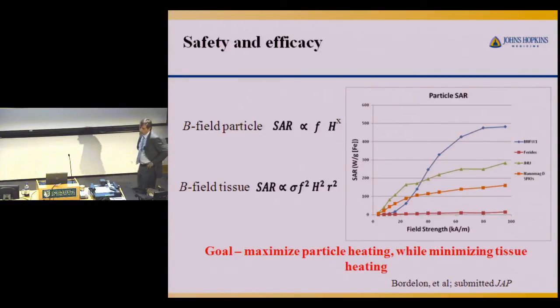When we put different particle formulations in an AC magnetic field, they're all iron oxides. They're all dextran or starch iron oxides. For some reason, we don't see the same result. That's because the magnetic properties, even though chemically these particles are essentially the same, are very different. The bottom curve, the red line, represents Feridex. Feridex is an FDA-approved MR contrast agent. It does not heat in an AC magnetic field. These are all the same conditions for all of the particles.